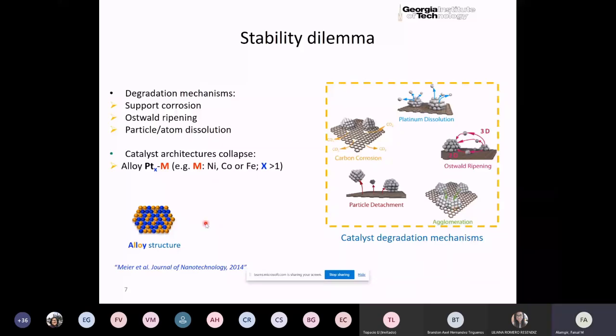So finally, one of the things that you could try to do, as we just discussed, is to tune the catalyst activity by alloying a second metal, a second material. So in this case, platinum can be alloyed with several other metals, and therefore you can try to get better activity. But the problem there is that the relative activity of the different elements over time has an effect of changing the composition of the catalyst. So in other words, for example, if we had iron or cobalt as one of the second elements, over time what you would see is that the cobalt is corroded away, and you'd be left with a shell of the platinum only.